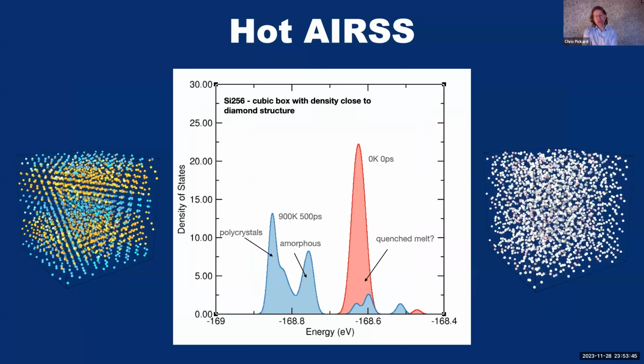And the red curve is normal AIRSS. So this actually emphasizes the limitations of random structure searching in very large unit cells. In a big enough unit cell, you start to mostly only explore the random melt-like or amorphous-like structures. They have the highest entropy. They take up the largest region of configuration space. And you have a very low probability of finding more ordered, lower energy structures.